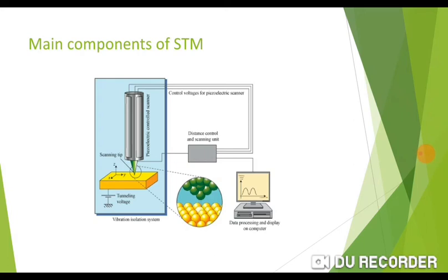The tip of the probe is a single atom, and the tip is generally made of tungsten. Generally, some electrochemical etching is used to create such a type of scanning tip. Now STM uses the feedback servo loop and converts the piezoelectricity to get the distance between the tip and the sample down to a couple of angstroms.